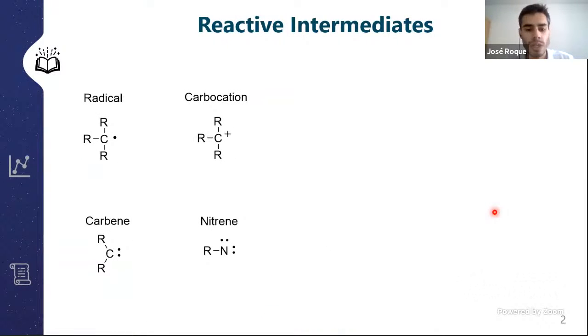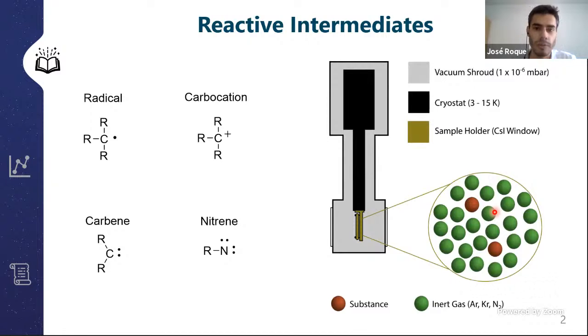The reason we got interested in these hydrogen tunneling reactions in the first place was because we were studying reactive intermediates such as radicals, carbocations, carbenes, nitrenes, among others. Of course, these molecules are very reactive, and their lifetime is very short under conventional laboratory conditions. But still, some groups try to characterize them through the use of time-resolved spectroscopies. But in our research group, we take an alternative approach, which is to try to enhance their stability and therefore their lifetime by using a method called matrix isolation.